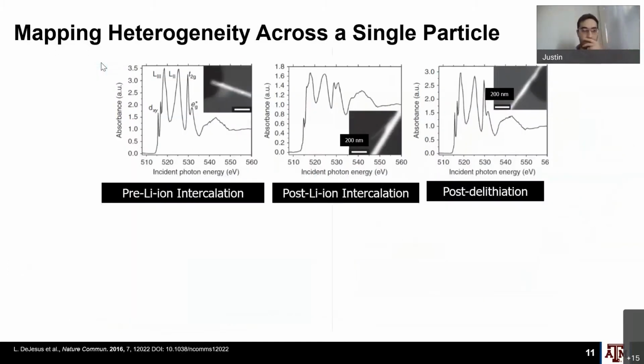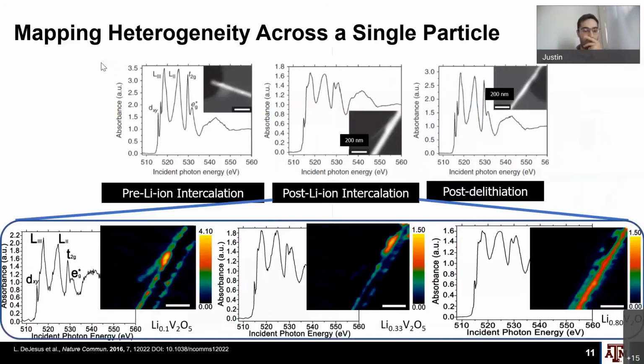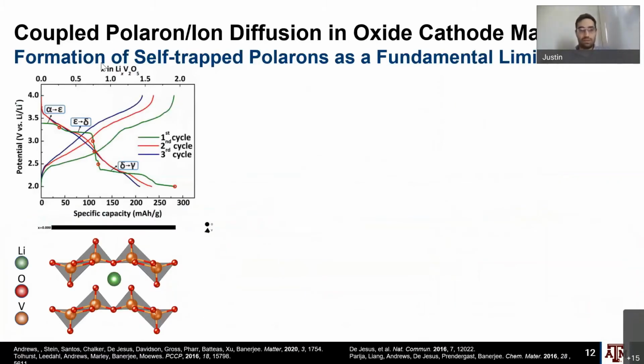And so going back to some of my predecessors' work, really early on, what we were able to do is map the different phase regimes within these materials, so we've got an idea of how these things lithiate. They tend to show these core-shell lithiation patterns, which is pretty consistent with what you'd expect for these kinds of layered materials as lithium intercalates from the outside. And if you look at these materials,